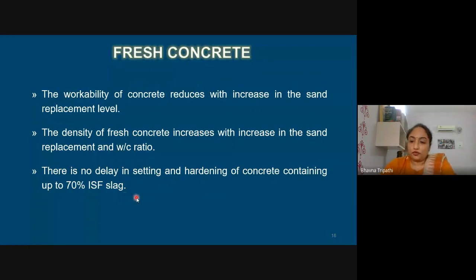And I did not mention the background, the previous studies on ISF slag. There are many studies which have reported that any kind of zinc or lead waste, when we add that to concrete and within a cement matrix, it delays setting. So this was the biggest concern for us when we started this work, that if ISF slag addition delays setting and hardening, and if it affects hydration, then we cannot recommend the use of ISF slag. However, we did not find any kind of delay, and there were no problems in setting and hardening.